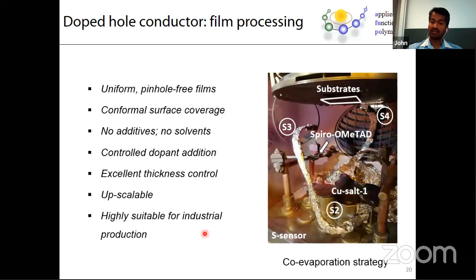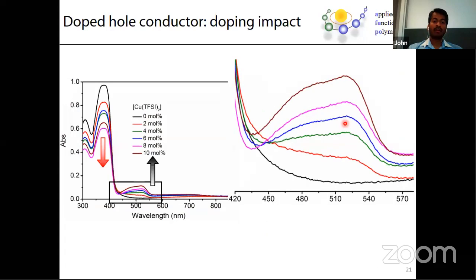And with this, so what we can do now, oh, sorry, before that, I wanted to show a clean, highly uniform film that was prepared by co-evaporating spiro and copper salt in this machine. Once the films were prepared, we also tested the oxidation process of spiro in films. Initially we had the idea that you take two materials and add them in solvent, where the solvent plays a vital role in stabilizing the oxidized species and helps them interact with each other. But when you go for co-evaporation, we are not certain whether this chemical reaction can happen in the gas phase, because this reaction should occur while they are moving from the source towards the substrate.